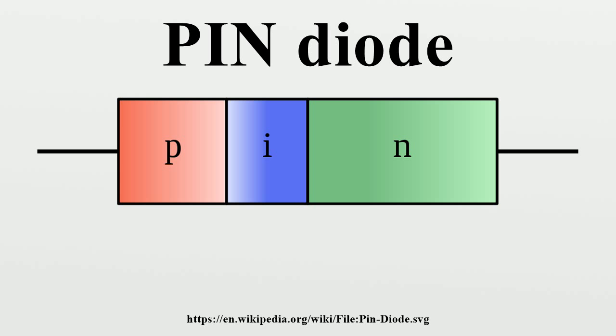Commercially available PIN photodiodes have quantum efficiencies above 80 to 90% in the telecom wavelength range, and are typically made of germanium or InGaAs. They feature fast response times, running into several tens of gigahertz, making them ideal for high-speed optical telecommunication applications. Similarly, silicon PIN photodiodes have even higher quantum efficiencies, but can only detect wavelengths below the band gap of silicon, i.e., ~1100 nanometers. Typically, amorphous silicon thin film cells use PIN structures.